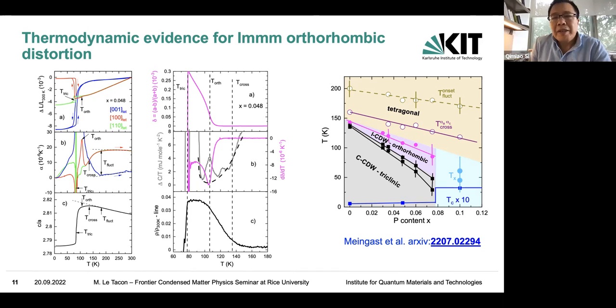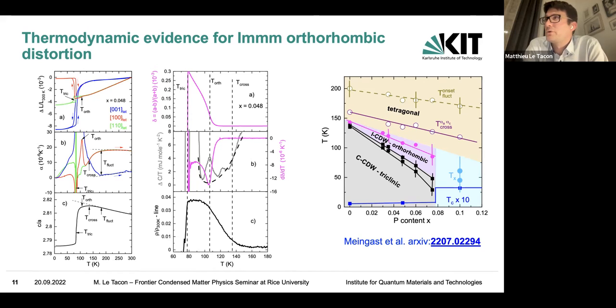Right. But I wonder whether there's a way to look at the amplitude of this CDW order versus the lattice distortion, and does that give some empirical evidence one way or the other? I mean, the lattice distortion is very, very small, but you do always have a coupling, right? I don't think it's possible to have a pure electronic modulation without the lattice being distorted with it.